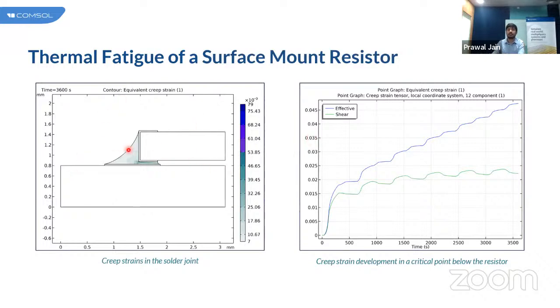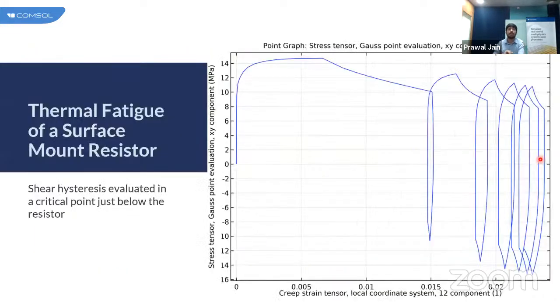Here we can see that the highest strains occur in the thin solder layer just below the resistor. It is mainly the shear strain component which contributes to the equivalent creep strain in that layer. The location of the highest strain agrees well with the crack path in the real application. In the figure, the equivalent creep strain and the shear creep strain components are shown. It is clear that the first cycle is not representative for the fatigue analysis, since its response differs significantly from the one experienced in the following cycles. We can see that even after six cycles of this repeated loading, the stress-strain curve has not stabilized.